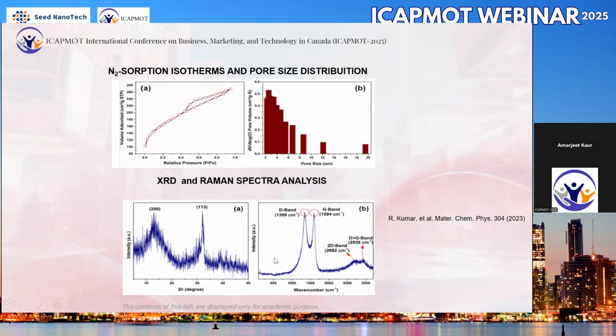So we did the Raman spectroscopy of the same powder, the same sample, and we have the D band and the G band. So we are getting both the peaks in the Raman spectroscopy. The D band indicates the degree of disorder in the material, whereas the graphitic band is related to sp2 hybridization. More than that, we have second order bands also, which are again a measure of disorder, and which is expected because we are not making any crystalline plane out of it. It's just amorphous carbon.